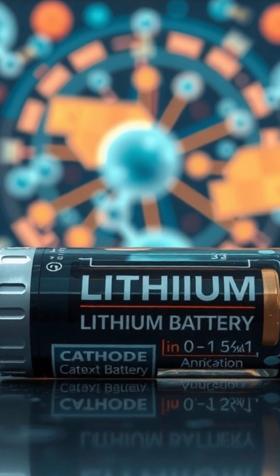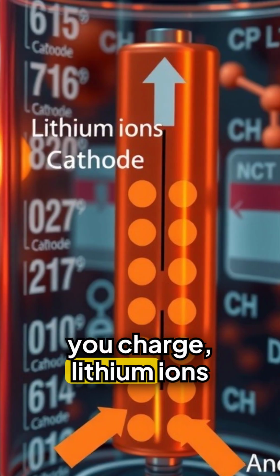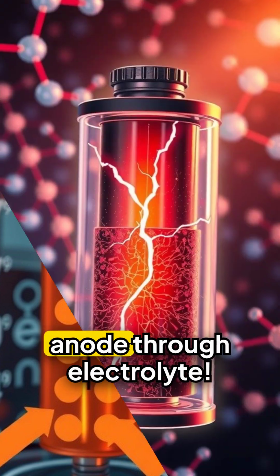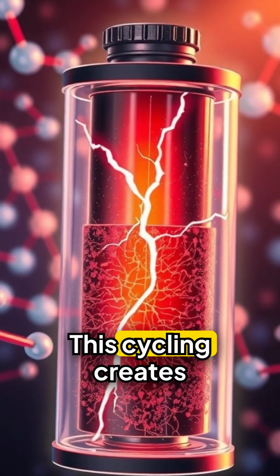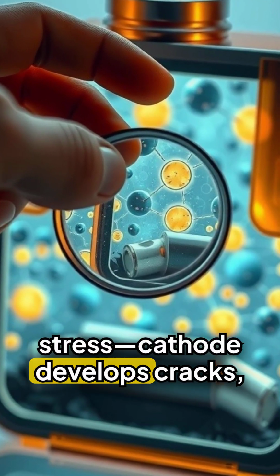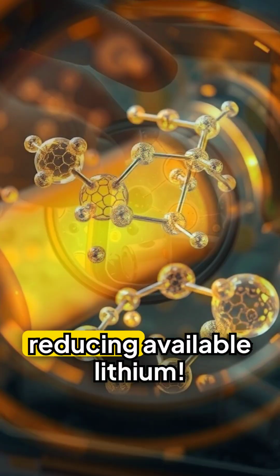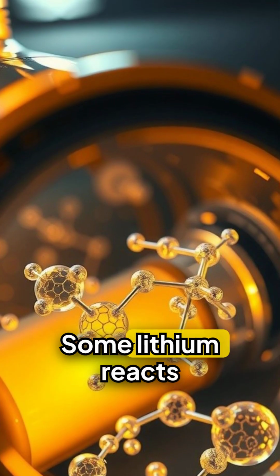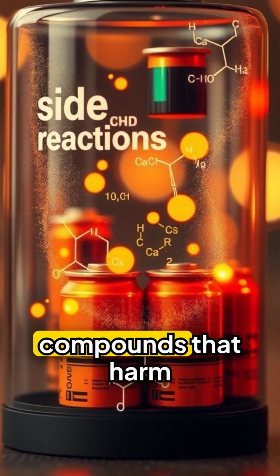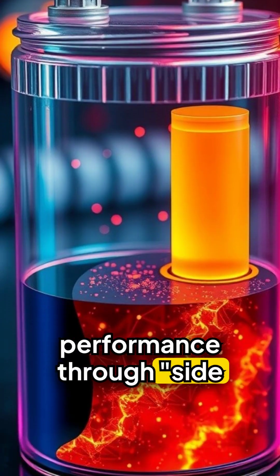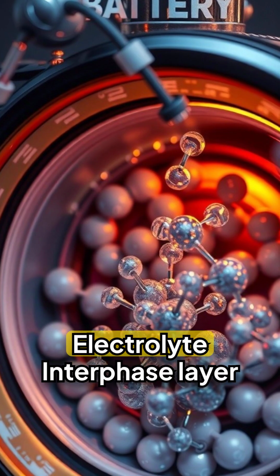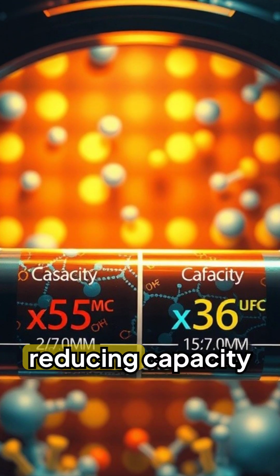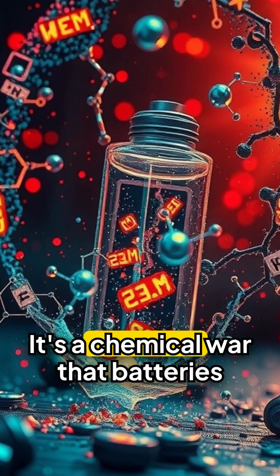Fact number two, the chemical war inside. Every time you charge, lithium ions migrate from cathode to anode through electrolyte. This cycling creates stress. Cathode develops cracks, loses structure, reducing available lithium. Some lithium reacts with other materials, forming compounds that harm performance through side reactions. The solid electrolyte interface layer on the anode traps active lithium ions permanently, reducing capacity from day one. It's a chemical war that batteries can't win.